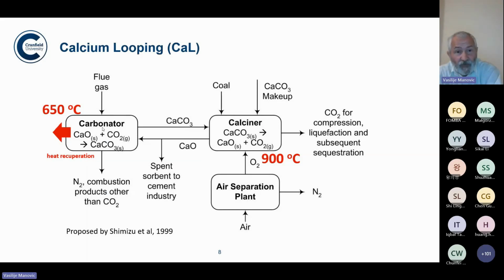So that's one reactor. We circulate material from the carbonator to another reactor, which we operate at, as we said, 900 centigrades. In that reactor, we have decomposition of partially carbonated calcium oxide. We decompose calcium carbonate and produce CO2. Now we need to heat this reactor. You see, we need 900 centigrades, and we cannot afford to heat this reactor like we usually do in a power plant, by air. We need pure oxygen.